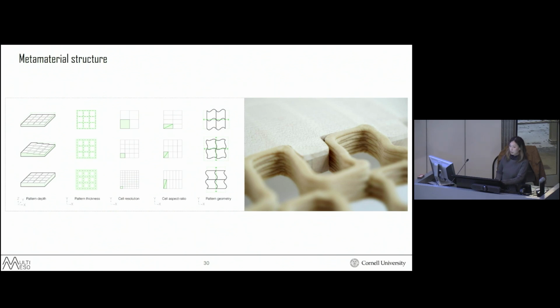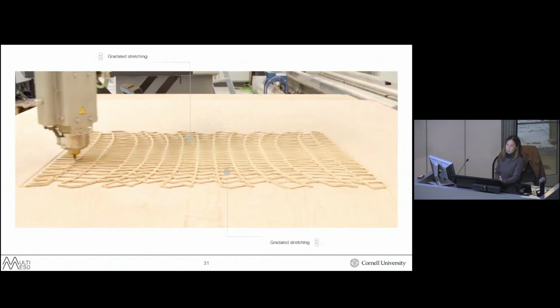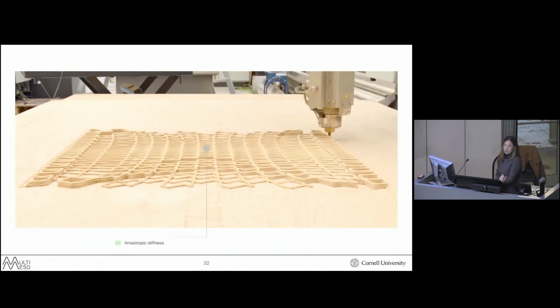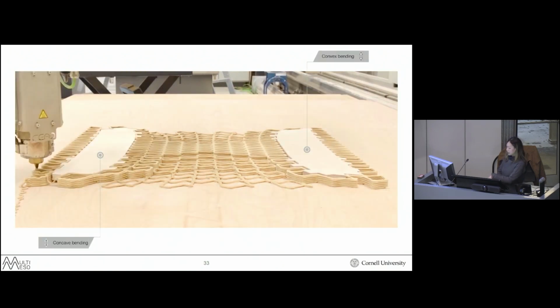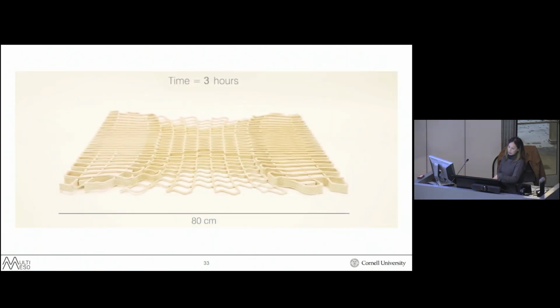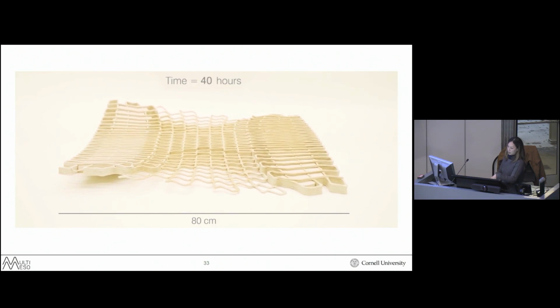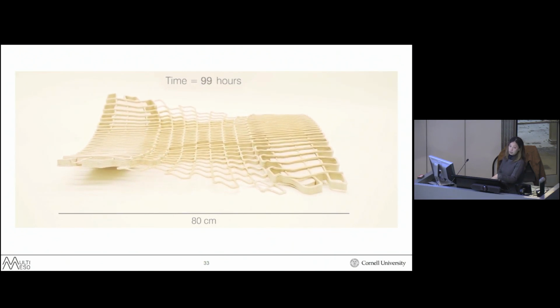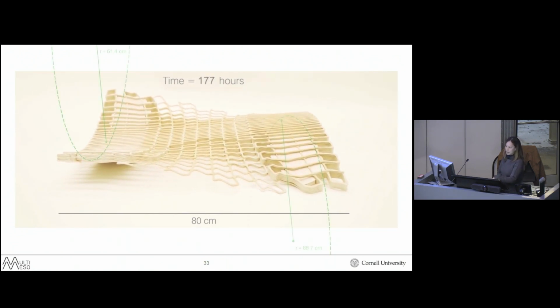So using geometry, we can then modulate those material properties in specific directions, such as physically programming areas that stretch in certain directions, areas of high stiffness, and also areas of bending in different directions. So this biocomposite structure, just by acclimating its moisture content to the ambient indoor conditions, transformed from the flat fabricated state to a very complex doubly curved shape without any mechanical force or operating energy.